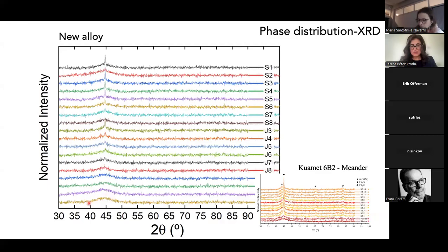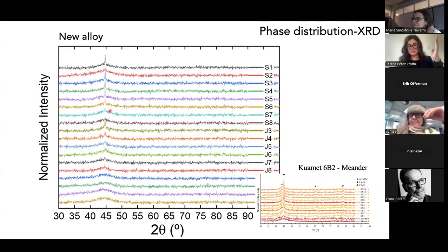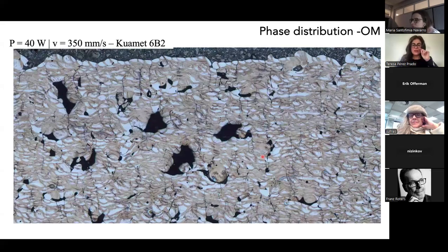So again, with this peak we can see here at 45, you can see now that for many conditions we do have what looks like an X-ray amorphous material. For others, we have some small crystalline peaks, but I put here what I showed you before, this stack of patterns corresponding to the commercial alloy. So you can see that the height and the magnitude of these peaks is much, much lower for these new alloys for a wide range of compositions here. Or sorry, a wide range of processing conditions, all this processability window that we explored. So it was looking quite good.